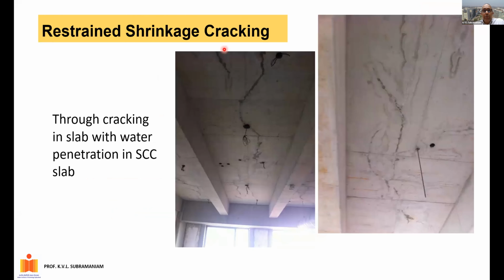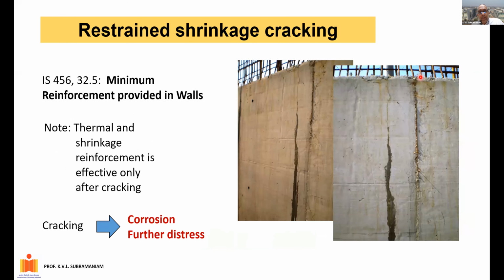And we are now seeing more and more of these shrinkage cracks appearing in structures, particularly where we're using this SCC, self-compacting concrete. And the reason for that has to do with the densification of the microstructure. We densify the microstructure to achieve one objective, but then it works against us when we are trying to control shrinkage. And more shrinkage cracking. This is in a retaining wall. This was even while the wall was being cast, and you can already see water is getting right through. And the steel would start corroding, and you can already see brown stains of steel corrosion on the surface of